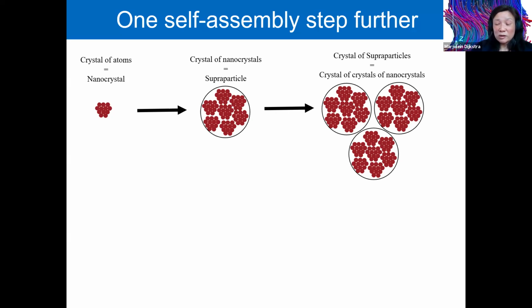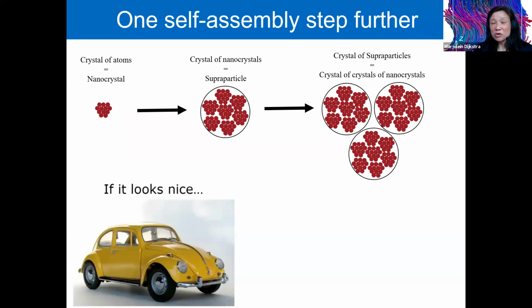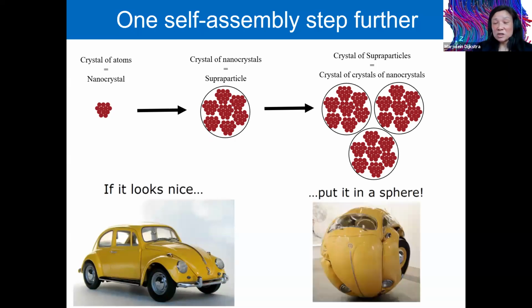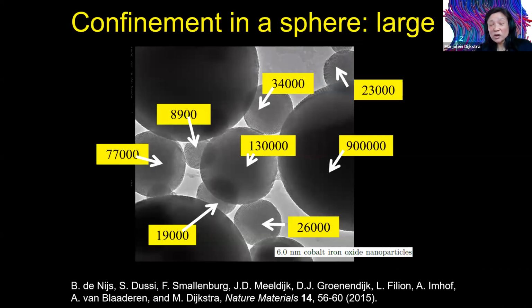And so this is more or less the motto that we use in our group. If something looks very nice, a nice particle shape or a nice structure, just put it in a sphere and you can make a supraparticle which can be used into a next self-assembly experiment. And so this is what we started several years ago. We used an emulsion. We can confine the nanoparticles into these emulsion droplets. Depending on the size of these emulsion droplets, there are different numbers of particles that we can confine into these emulsion droplets. Here we can see that we have 130,000 particles, or smaller droplets contained 8,900 particles.